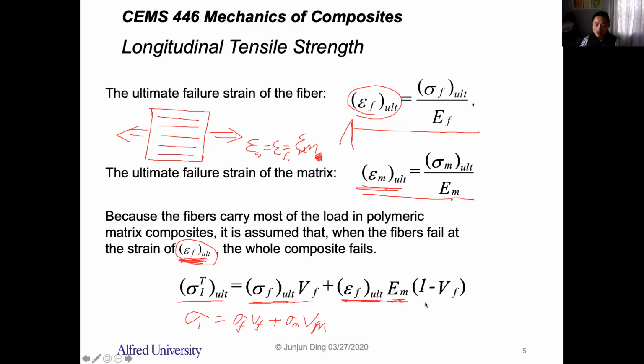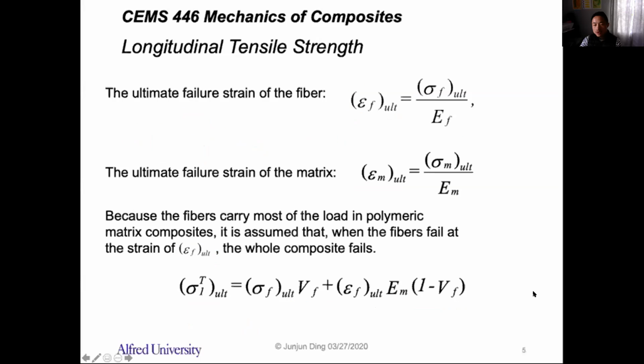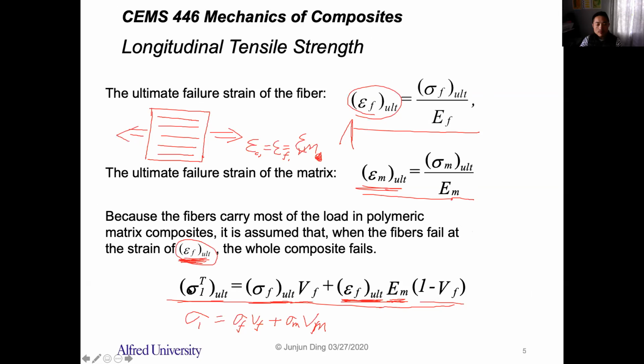And if there's no void, the volume fraction of the matrix will be 1 minus VF, right? So this is true to calculate the ultimate strength of the composite in the longitudinal direction, right? Tensile strength.